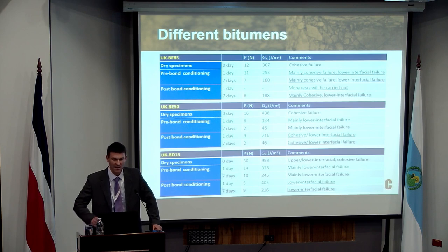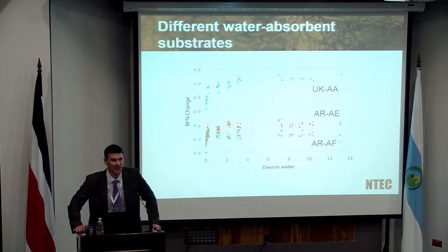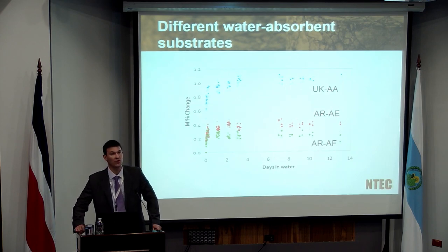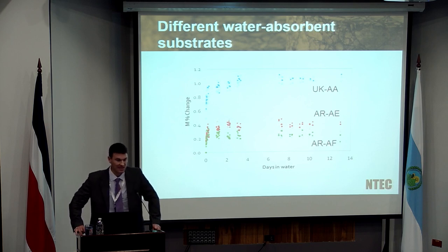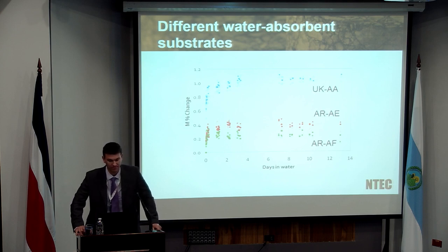But obviously, we were very interested in using this test to differentiate between different types of aggregate. And the first thing to remember is that these aggregates have different water diffusion rates. In other words, water moves through them and is potentially available at the interface between the stone and the bitumen at different rates. So the first thing we did was determine what that diffusion rate was for the range of materials that we're interested in. This is just three examples.